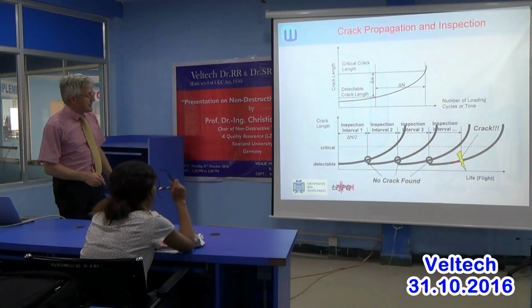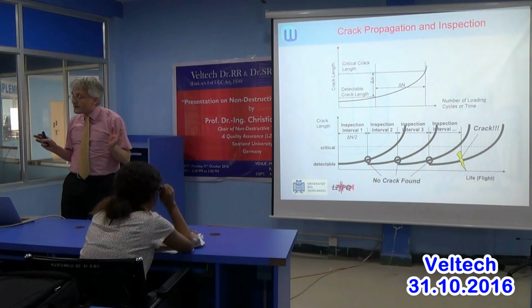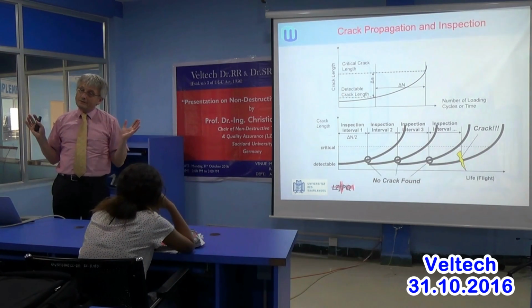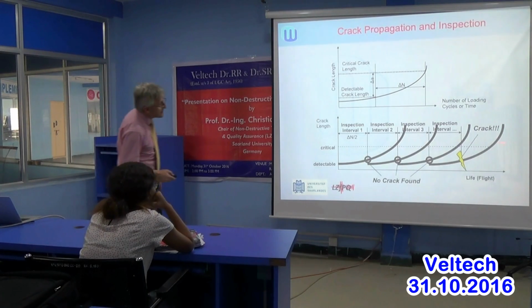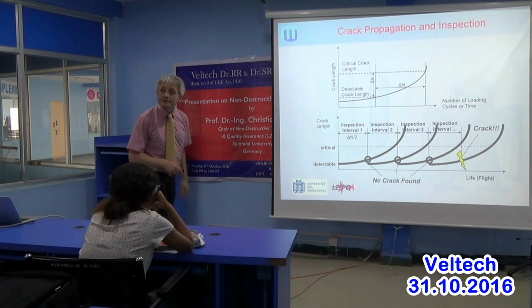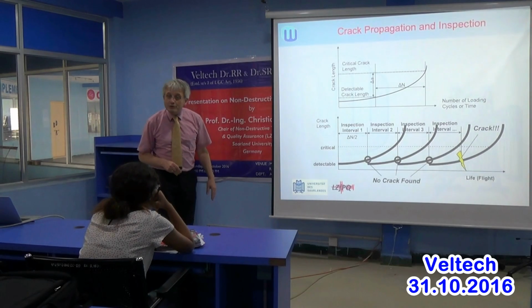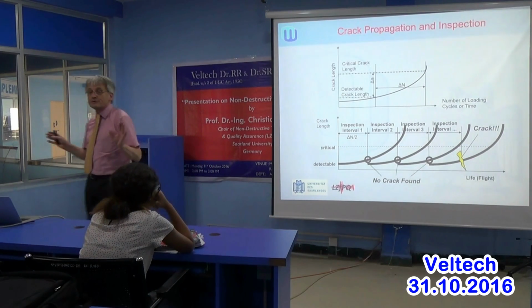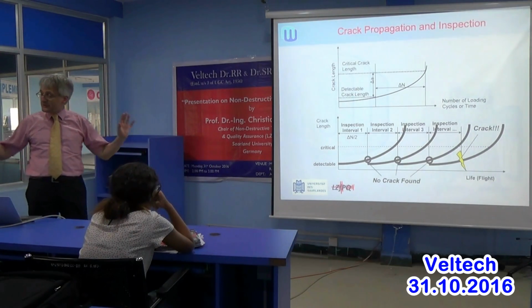So that's what has happened here. And if we find a crack, then we have to repair. But the crack is still not critical, right? Because it's smaller than this crack. And this is what we call damage tolerant design. So you realize inspection in that case plays a big role.